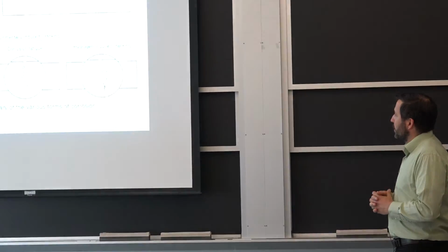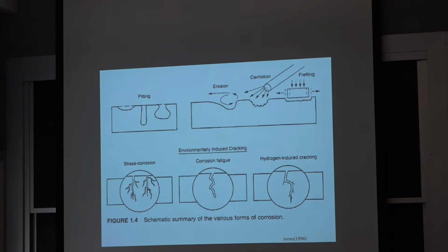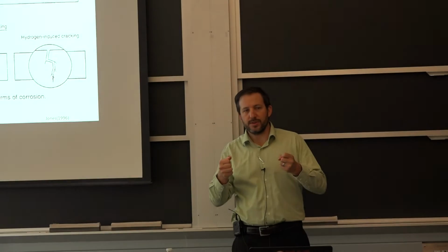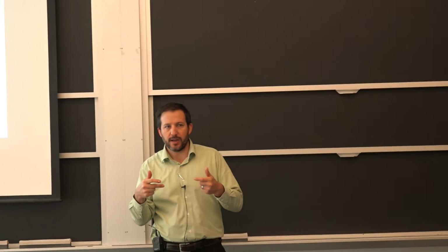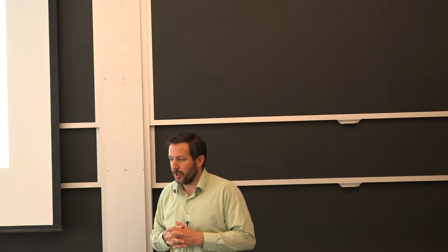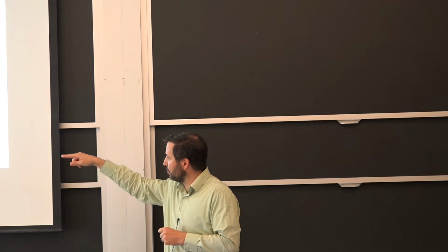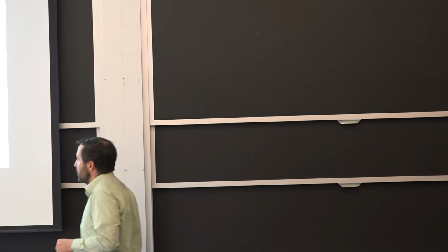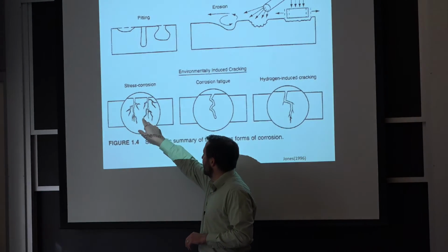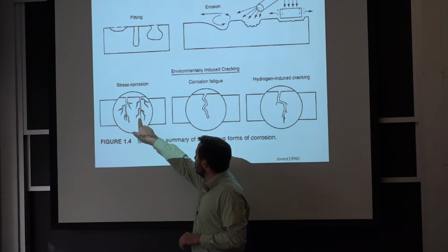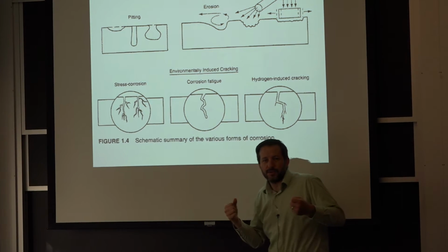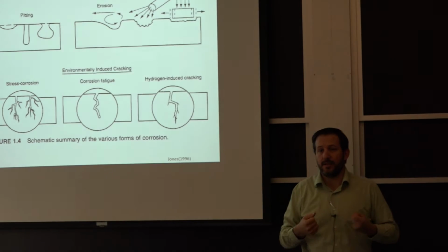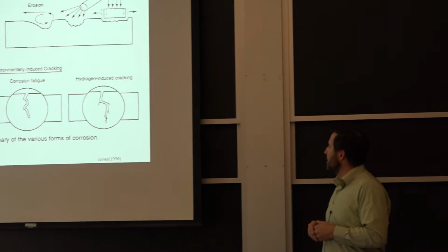of a protective film. And then the environmental cracking, if it's stress corrosion, it's just a constant load. And this is something we've talked about, where if you have enough force applied, then your rate of growth of that crack is very constant. What really needs to happen is the diffusion of the reaction product to the tip of the crack. As long as you can supply these three cracks with the same reactant, they all continue to go, even though normally this one is a little bit protected by the other, so it definitely has less stress intensity on it, and so you'd expect it to stop, but it won't a lot of the time.